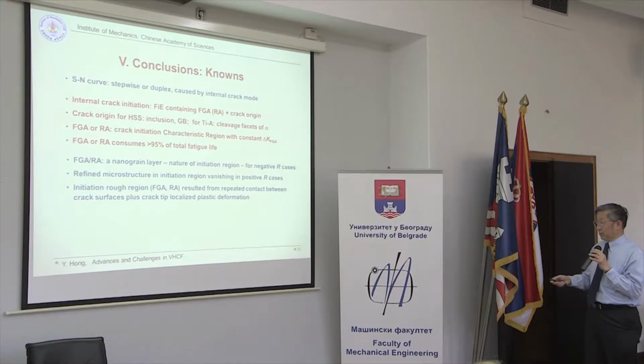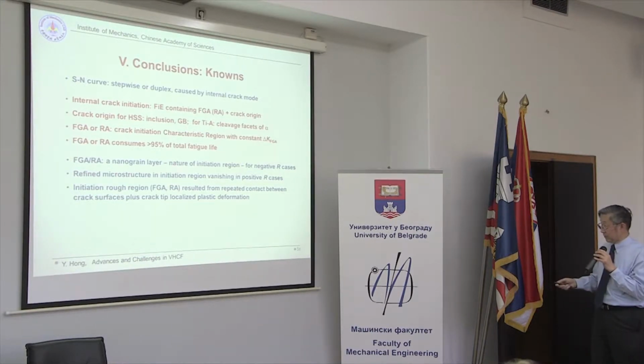And FGA is, we said, our emphasized point, a crack initiation characteristic region. And the related value of delta K is quite stable. And this region is more than 95% of total fatigue life. And this initiation region is a nanograin layer. And it is in relation to negative stress ratio cases. But for positive stress ratios, there's no evidence of grain refinement.